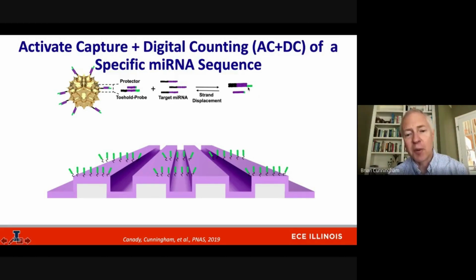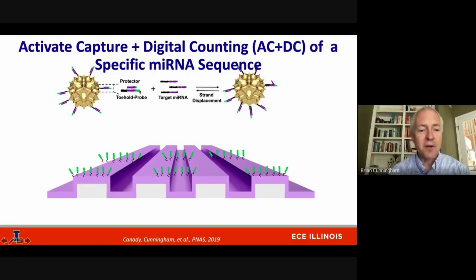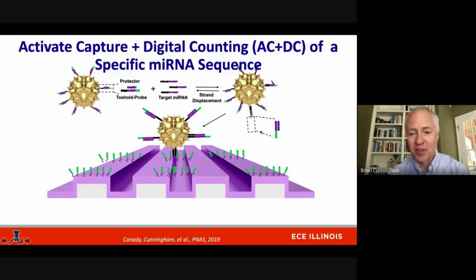This nucleic acid sequence represented here in green that used to be protected by the protector is now exposed. Now we've chosen this sequence of nucleic acids strategically to be a complement to the nucleic acid sequence that we've already prepared on our photonic crystal. And so exposure of the toehold probes on the nanourchins to the test sample, one target microRNA molecule results in activation of one gold nanourchin particle that can now be captured on the photonic crystal surface only when this green sequence is exposed. So basically, this is an assay that converts one target microRNA molecule into one surface-attached gold nanourchin nanoparticle that we can subsequently count with our new form of microscopy.